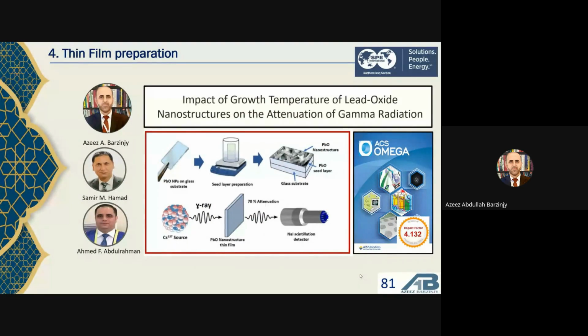And also we could utilize nanoparticle in order to absorb the gamma ray. In this case, gamma ray is very problematic, it is a nuclear problem. So this is gamma radiation, and then we could produce a film from PbO, lead oxide nanostructure film, and after passing gamma ray, 70% of this gamma ray has been absorbed by our film.